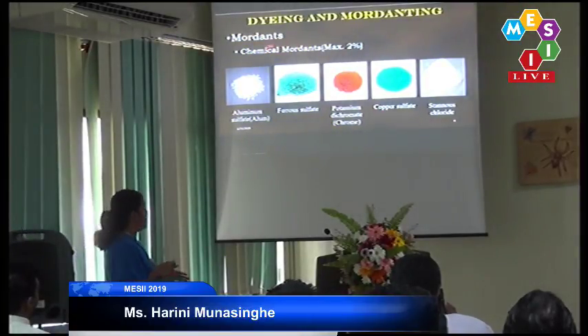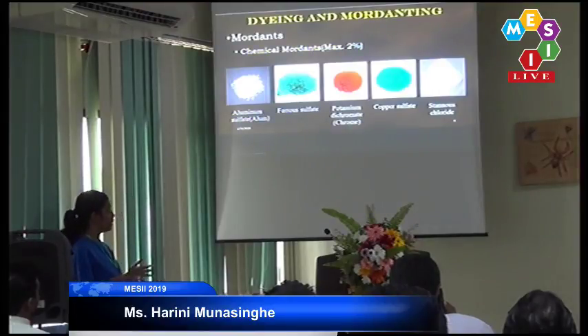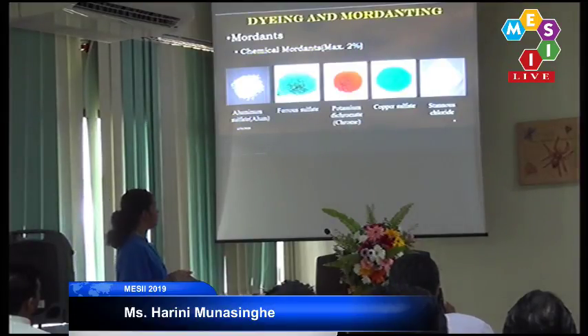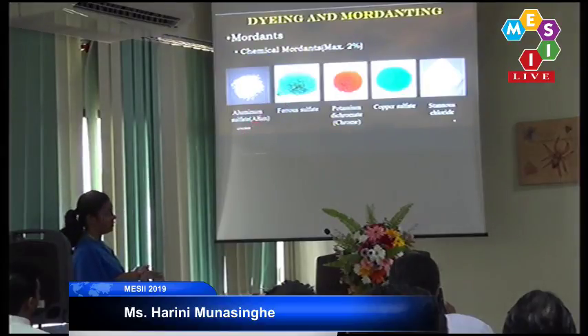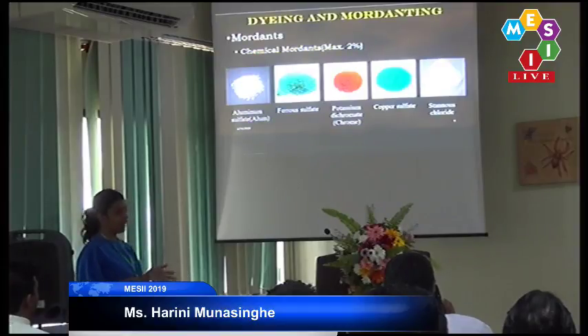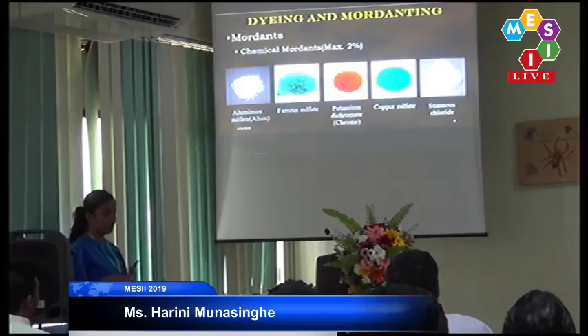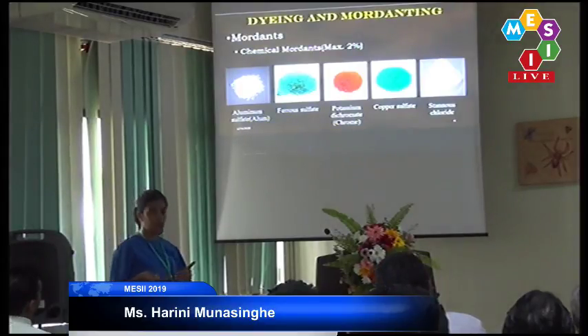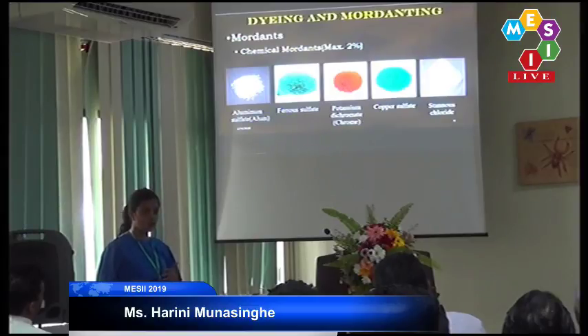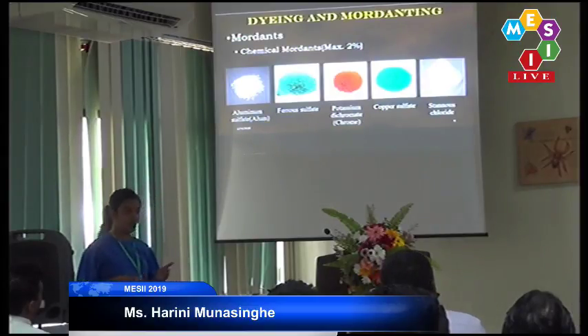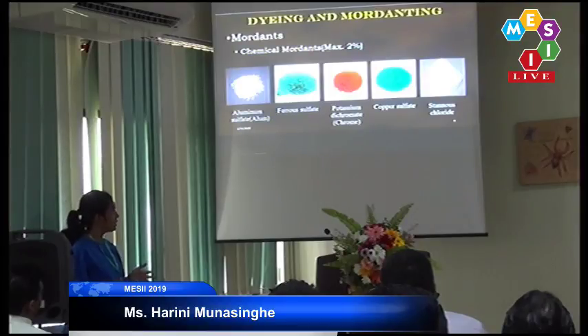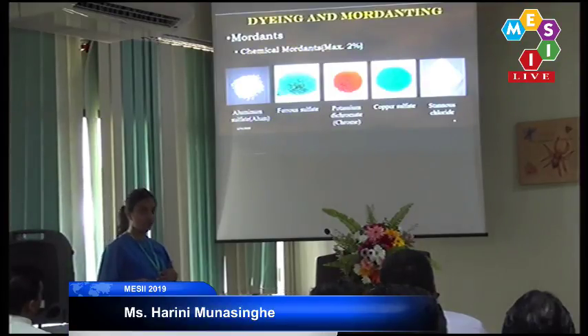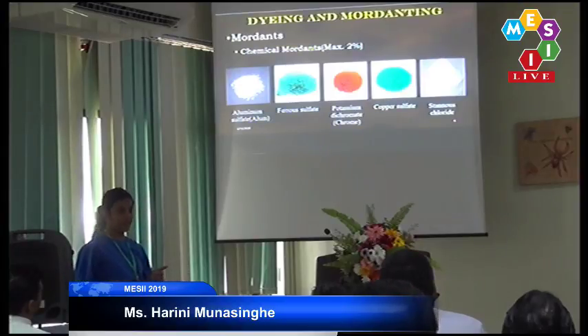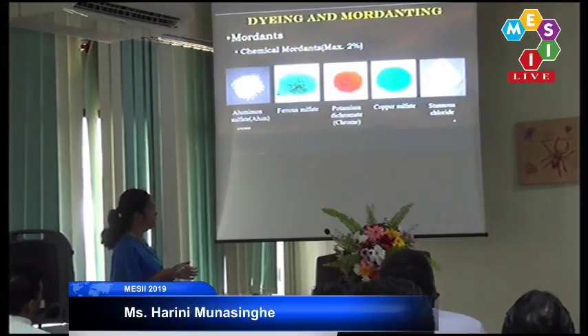Before I explain what a mordant is, here I am going to tell you what the mordants we use in this process are. We use aluminium sulfate, which is known as alum, ferrous sulfate, potassium dichromate, copper sulfate and stannous chloride. Here I need to mention that if the concentration of these chemical mordants is below 2%, it's not toxic and harmful. Because of that, in this dyeing process, the concentration of these metallic salts we use is below 2%. Because of that, it does not affect the toxicity of the natural dye.